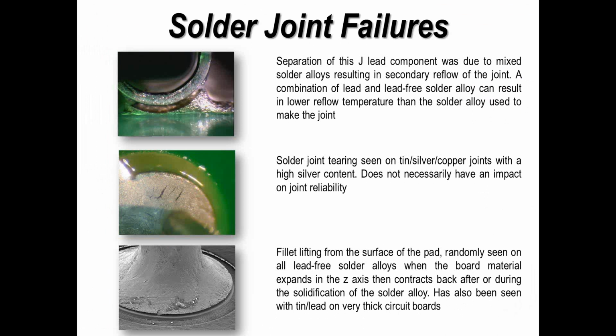A couple of other examples. Now these are, in my opinion, the middle one and the bottom one are not really failures. These are what you can see. So if you're running a tin silver copper soldering operation, be it reflow or selective or wave, and you're using a high silver content material, you can get what people refer to as tearing, where between the grain boundaries you're getting tear lines within the bulk of the solder.